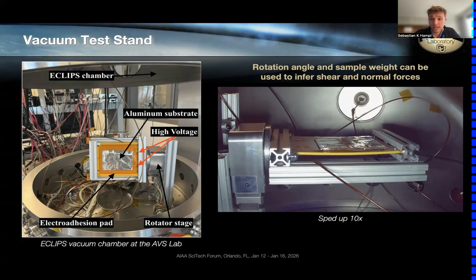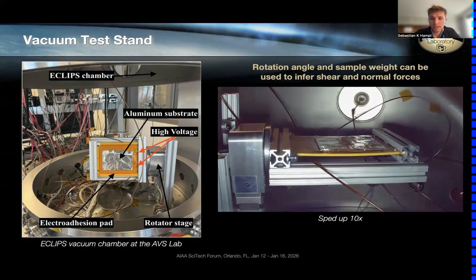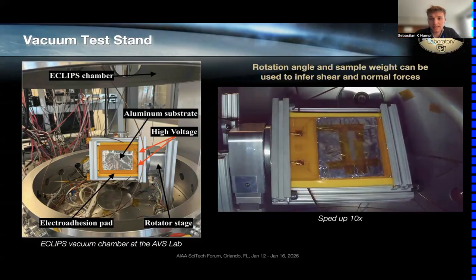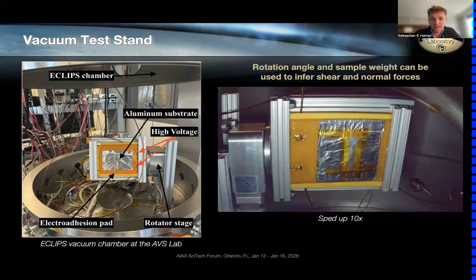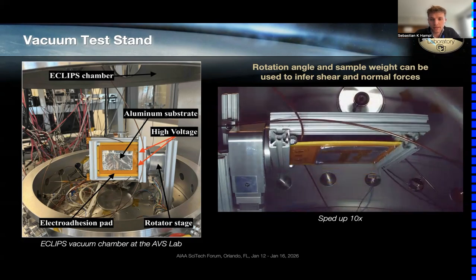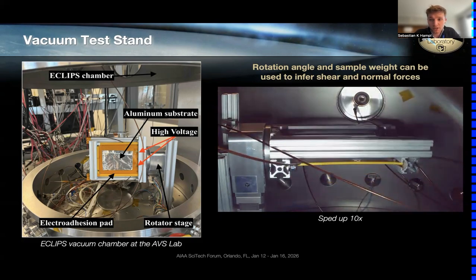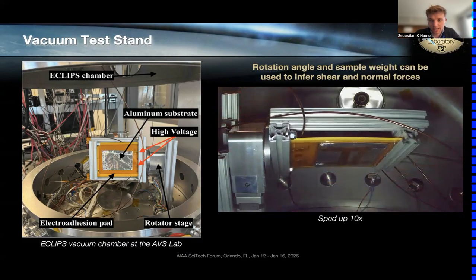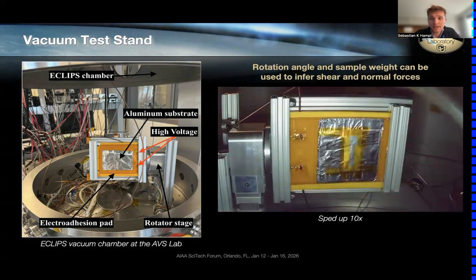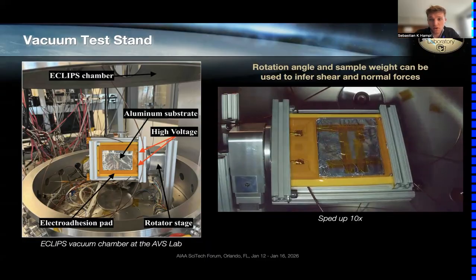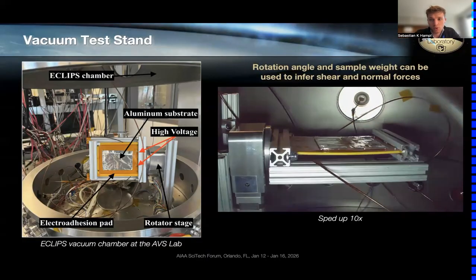We chose to use a rotator test setup where a sample is placed onto an electroadhesion pad and then uses gravitational preloading. And then we apply the voltage and rotate it by ideally 180 degrees in the vacuum chamber. We can deduce from the rotation angle where the sample falls off what the maximum shear and normal forces that we can get from this electroadhesion pad are. And in general, the higher the rotation angle is, the closer to 180 degrees, the better the performance, and the higher the achieved electroadhesion forces.